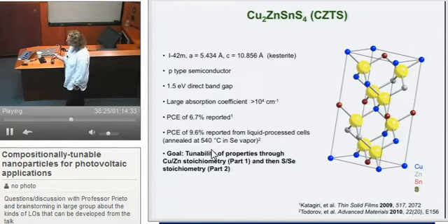So the question was, could we develop a solution phase method to make particles of this compound? And then really importantly, what I wanted to try to figure out is, could we tune the copper to zinc stoichiometry? That was predicted by theory to improve the absorption coefficient. So the theory was that if you could make copper deficient, zinc-rich compounds, they would absorb light more efficiently. And then the second part was, could we tune the sulfur and selenium? And I'll come back to that.